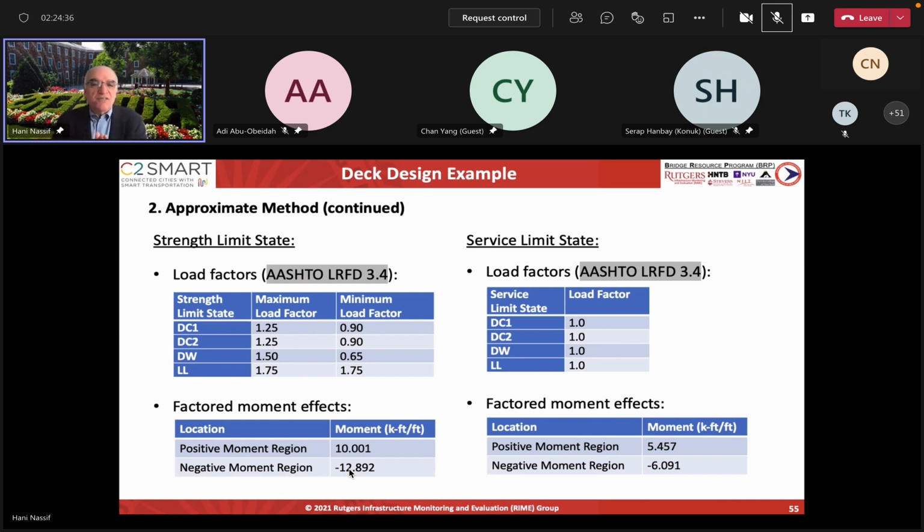Because it was found that with the ingress of chlorides into the concrete, if the crack is less than 0.016, there will be no corrosion induced into the reinforcement. So that's what this equation is based upon. It's an equation that ACI adopted, by my colleague Robert Frosch from Purdue, and that was based on a physical model of how the deck will crack.